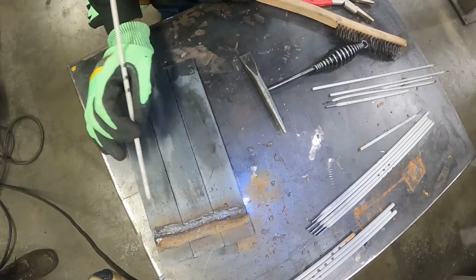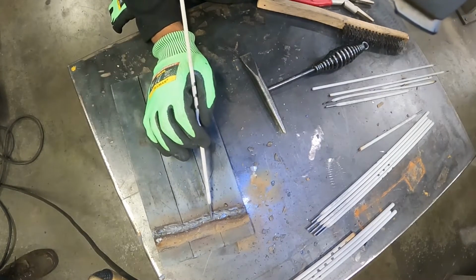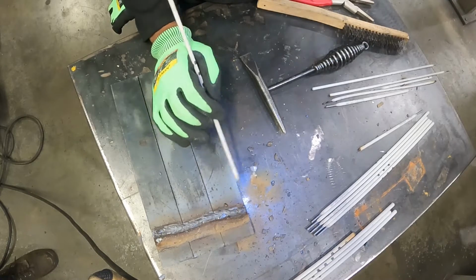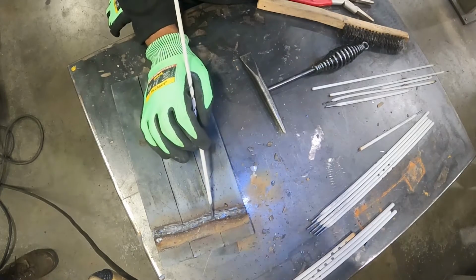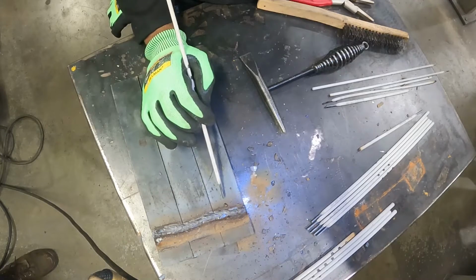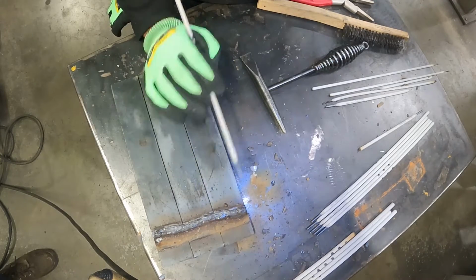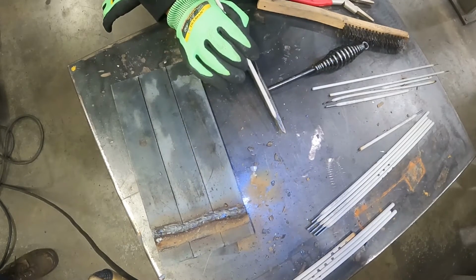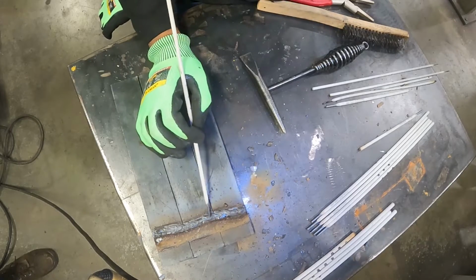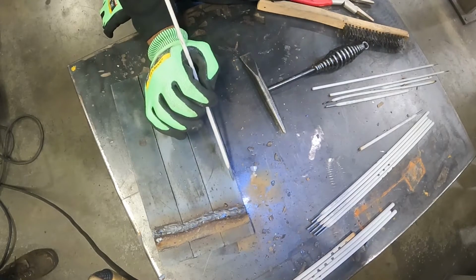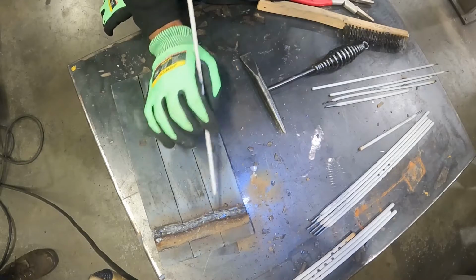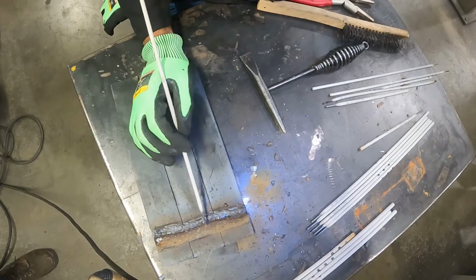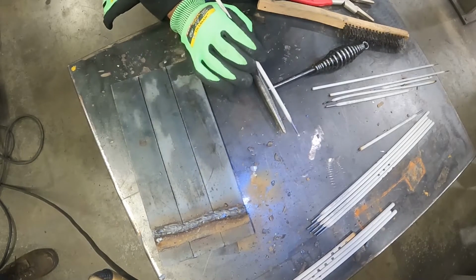And then the other thing we notice is the pattern, the shape of the ripples in the weld. They are like V-shaped, okay? And what that means is that you're traveling too fast. Your travel speed is too fast when you have V-shaped ripples or U-shaped ripples, okay? They should be more circular or oval, okay?